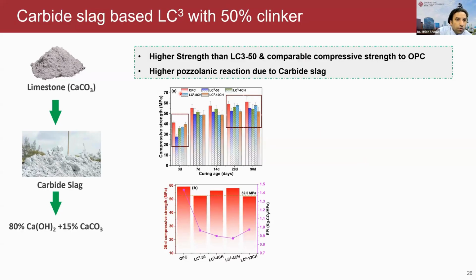If you see in figure A that there's a significant increase in the early age strength when we use this calcium carbide, which is totally a waste material, and it can significantly boost the early compressive strength, which is also a major issue in this kind of low clinker cement. So it provides very promising results to us.